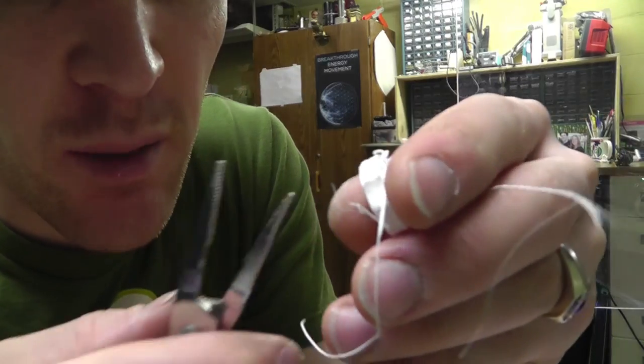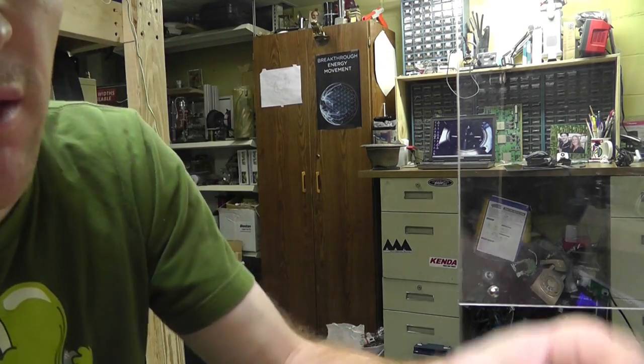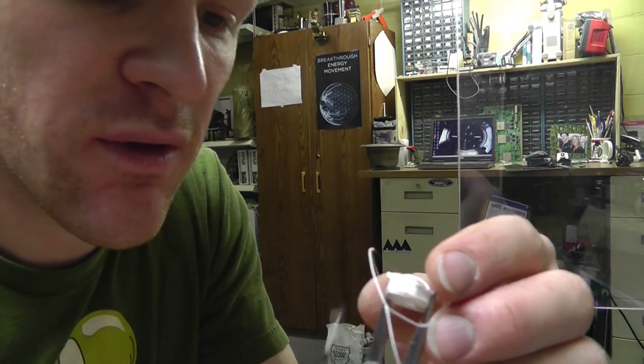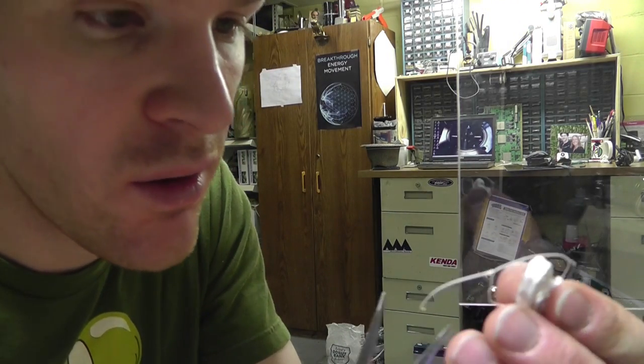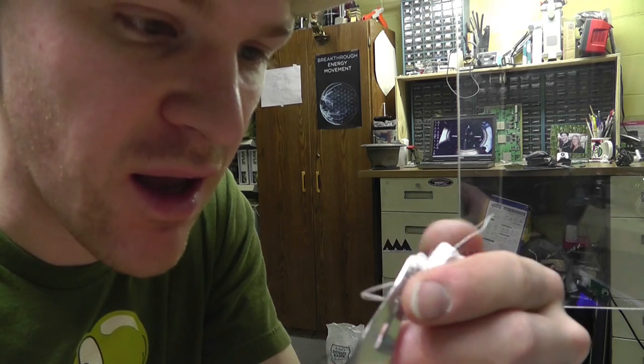Okay. I printed one at a higher temperature. I went down to, I usually do 230. I went down to 224, and it delaminated, but not as good here. Then I went up to 236. And it looks a lot better. So, now I'm gonna try it even a little bit, even higher. And we'll see what that looks like.